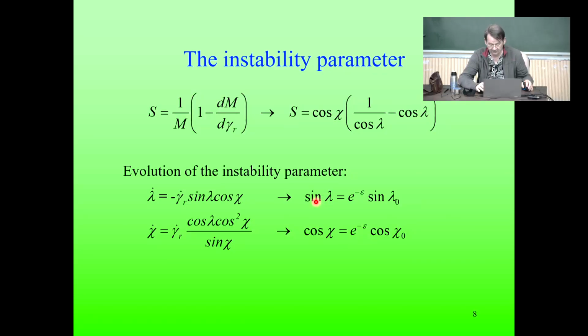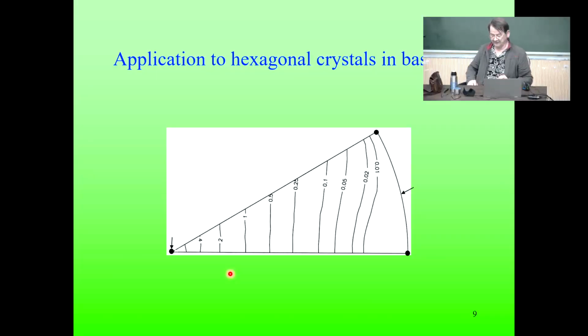Continuing the analytical calculation, we have its evolution equation as a function of strain. Epsilon is the strain in tensile testing. And the whole calculation is analytical. In this way, we get the instability parameter as a function of strain, where you see the initial orientation of the slip system, and then this is the strain, that's the instability parameter. But one can also make a plot for different crystal systems. You looked at hexagonal, like zinc is hexagonal, and in basal slip, it is deforming very nicely, easily, and making a lot of deformation.